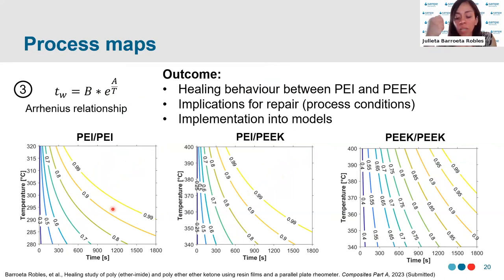So for example, if we think of what was done back in the mid-90s with the thermobond process, they did a repair that took 30 minutes. So by taking that time, if we have a big structure and we target 30 minutes, then that means that we need a temperature of at least 370 to obtain a degree of healing of one. So this would most likely melt the parent structure and induce voids and delaminations.